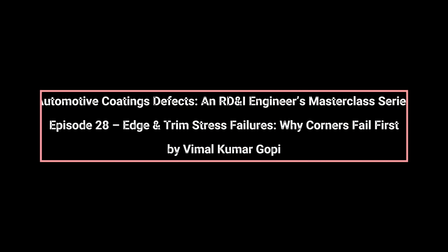Edge and trim failures are among the most common complaint categories in automotive coatings, yet they are often misunderstood. Customers notice peeling, chipping, or corrosion along panel edges, hem flanges, and trim interfaces and assume the coating is defective. From an OEM perspective, these failures are highly predictable because edges concentrate mechanical, chemical, and thermal stress, creating conditions where coatings are most likely to fail first.